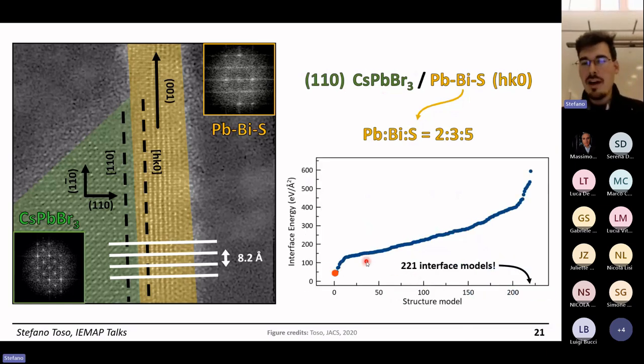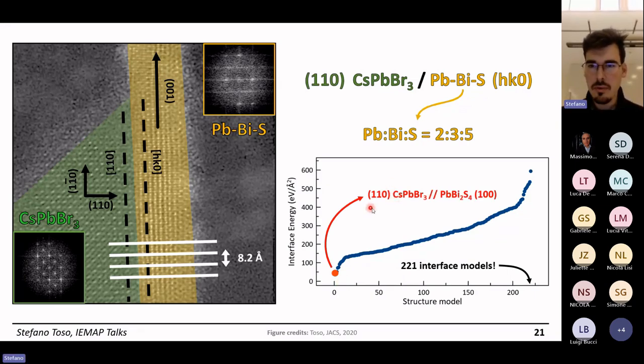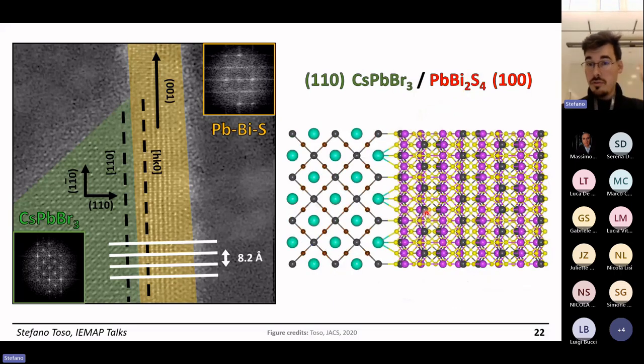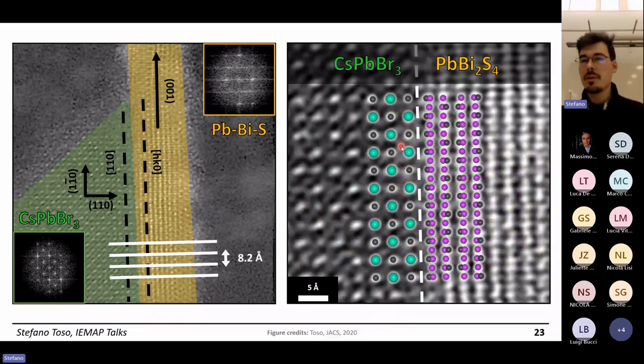But we could actually simulate all these 200 models on my laptop in a couple of hours. This is a remarkable result, because usually, even with DFT on a supercomputer, it would take a while, but this potential is really fast. And when you rank all of them by energy, you have a clear winner. You have a structure that is lowest with respect to all the others. It's this structure here, 110 cesium lead bromide, PbBi2S4 (100), galenobismuthite. And when you check the crystal structure, you see that it's nicely connected. There is low strain. There are bonds forming at the interface. You overlap it to your initial experimental information, and it matches perfectly.